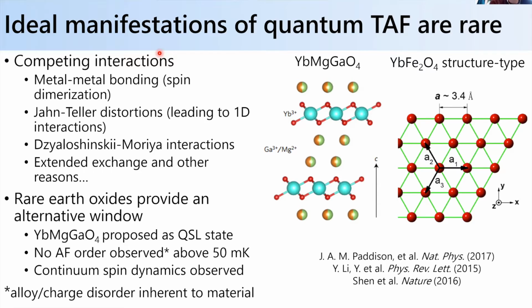Other effects such as Jahn-Teller distortions can basically break the degeneracy of the equivalent exchange pathways. So you can lead to 1D exchange interactions. You can have antisymmetric exchange interactions such as Dzyaloshinskii-Moriya, which eventually lift the frustration at low enough temperatures. And then, of course, depending on the orbital extent of your magnetic ions, you can have extended exchange that can also serve to lift the frustration of the lattice.